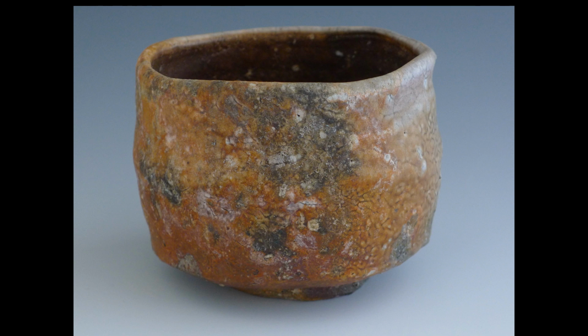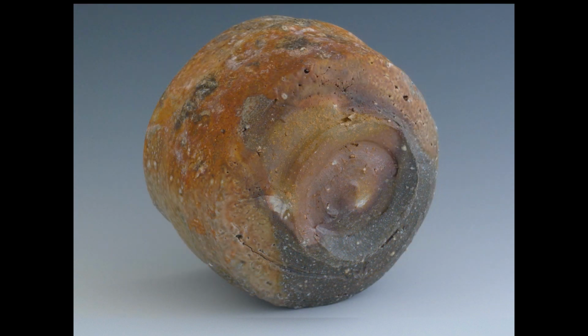This is a flashing Shino slip piece. This kind of bruised orange color is very rare. I've probably gotten it 3 or 4 times over the years. And it seems to occur again on the floor very close to the exit flues in the back of the anagama chamber, and sometimes just inside the Noborigama chamber as well. So those are some possible areas that this occurs, and it occurs at a lower temperature. It doesn't happen at the very high cone 13 temperatures. So it has to be further back in the kiln and a bit away from the actual burning wood of the firing. Here's another view of it.